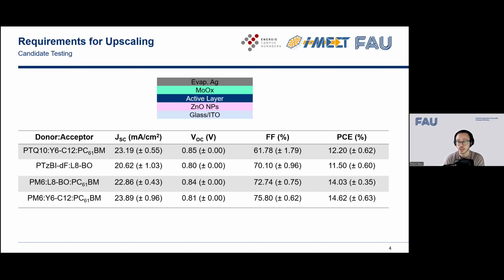And also a VOC again is quite nice. So here we are already at an average of slightly over 14% in PCE. And then we replace the L8BO by Y12. Both molecules are actually quite close to each other structure-wise.